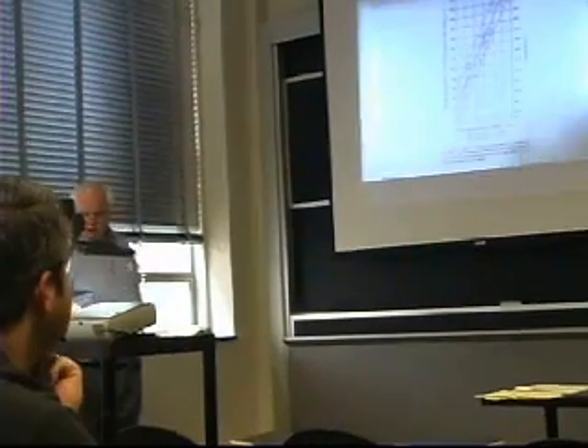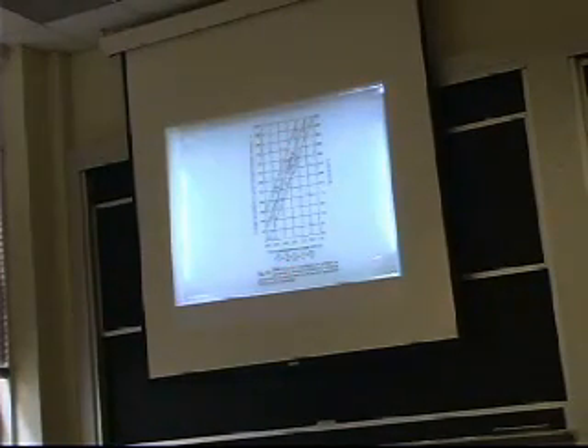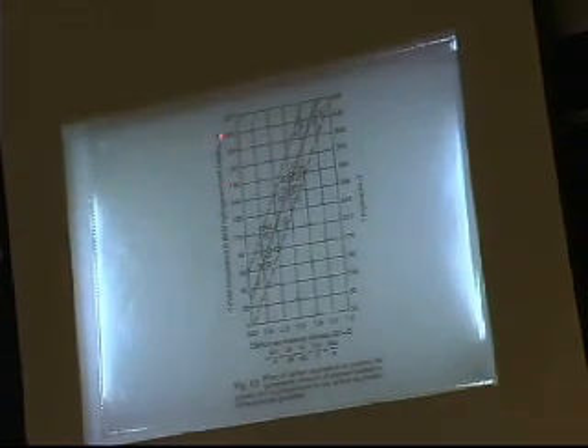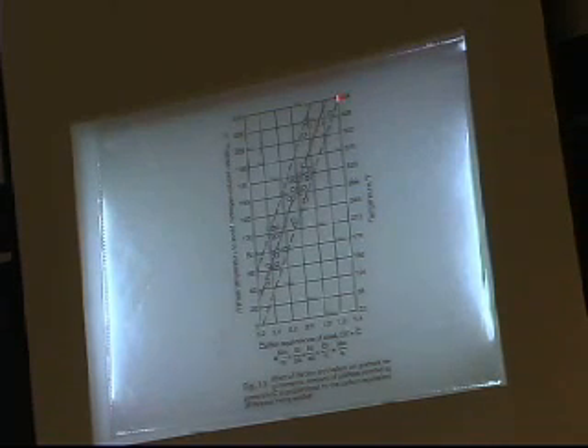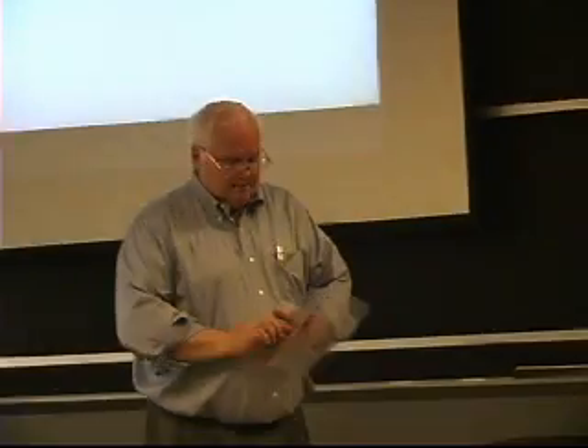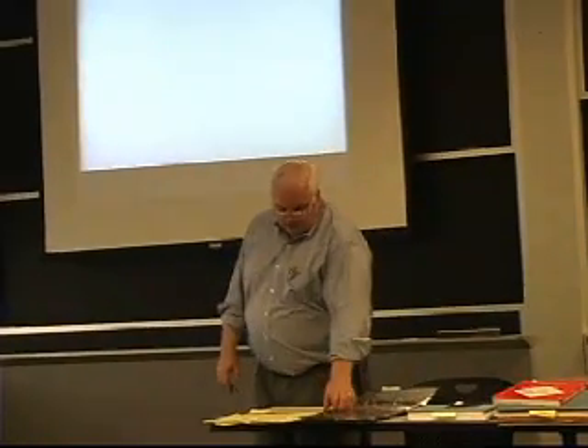This is a similar type of plot. You say, gee, it looks like the plot he just showed me for the cast irons. But it's not. This actually is I think from the Structural Welding Code Appendix. But here's your carbon equivalent formula: preheat temperature to avoid hydrogen-induced cracking versus carbon equivalents. And it's got a nice steep slope like this. It only goes up to, well, it does go up to 400 degrees. And it shows a bunch of different steels in here. Okay? So you have to know which steel you're welding. There are recipes, they're well known. Still, officially, each company is responsible for their own recipe.